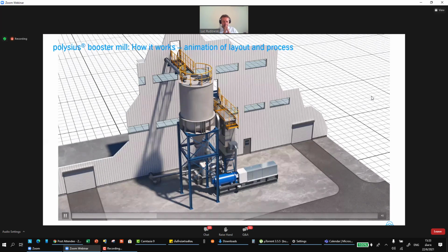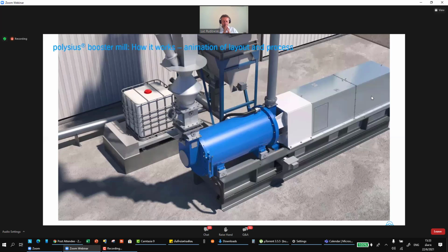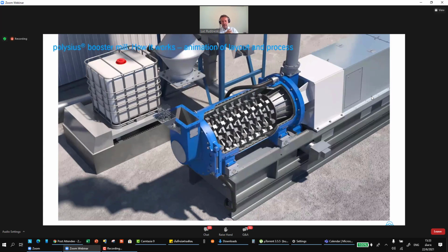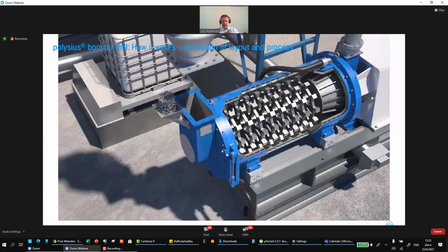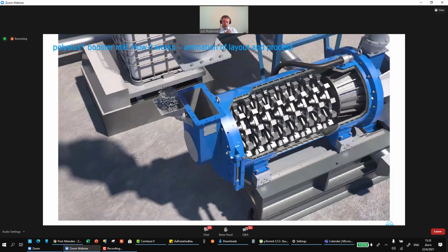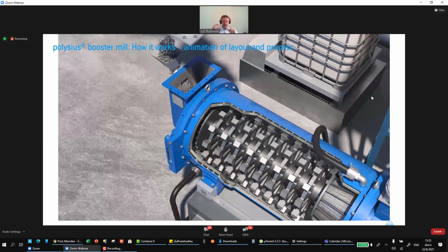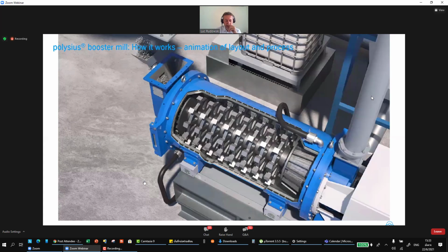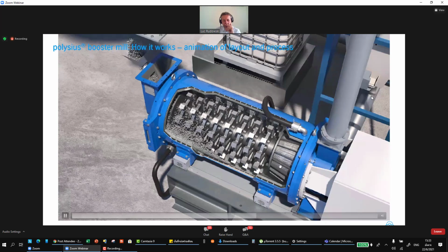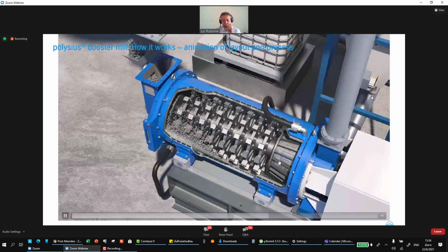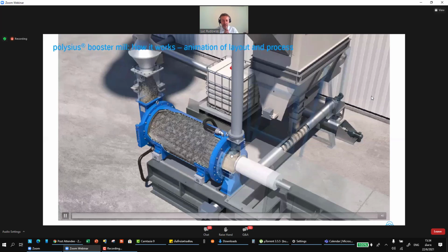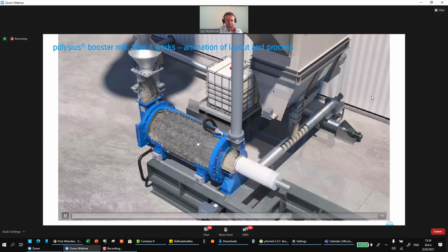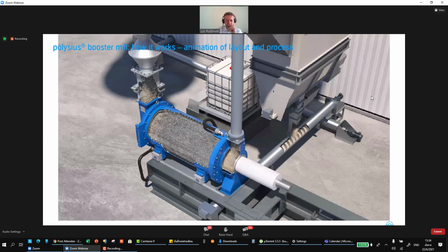So as you can see, it's a small chamber with rotating grinding discs there. So here we are on the small velocity with feeding of the beads, these very small 6 to 8 millimeter balls here. So the velocity is quite small. So you have this grinding chamber here, and you have at the outlet a trommel to separate the beads from the material. And when we feed the material, then the velocity of the grinding ring is accelerating, and with a very high energy density. I mean, the power to volume ratio when compared to a ball mill is 10 times higher. So you can imagine that the grinding efficiency of such a system is extremely good.